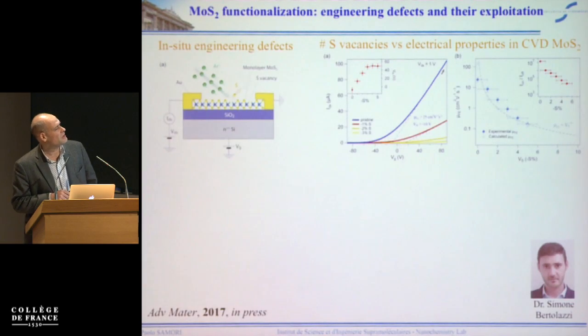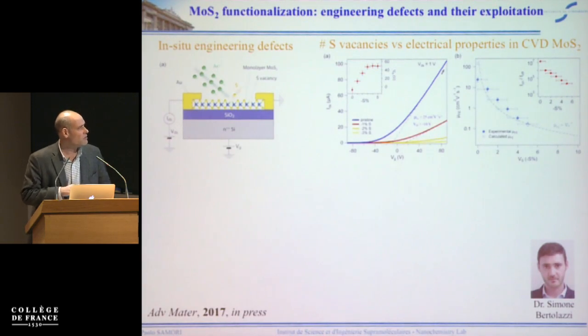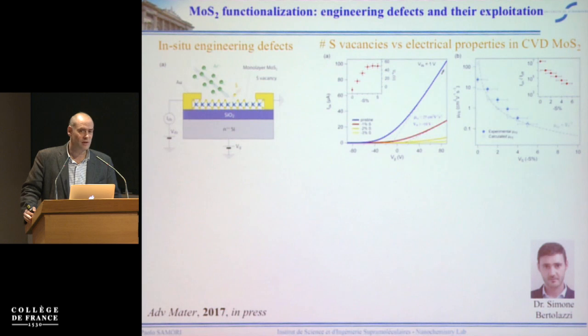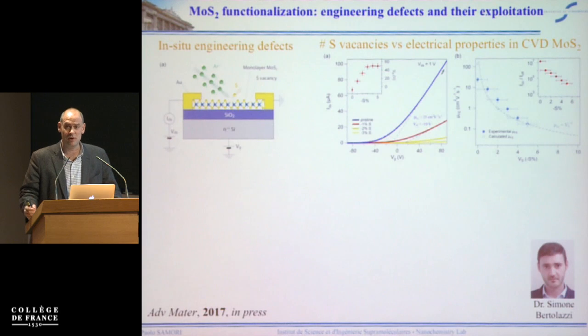So this is just a very recent work that we have published. And the idea is very simple: you start from molybdenum disulfide. You can buy the CVD, or you can have a Scotch tape, and there are a certain number of sulfur vacancies. Now, this number of sulfur vacancies can be used in order to attach thiolated molecules to this. Now, you might be unhappy with the number of sulfur vacancies that you have, and so the question is, can you increase them? And the answer is, of course, yes.